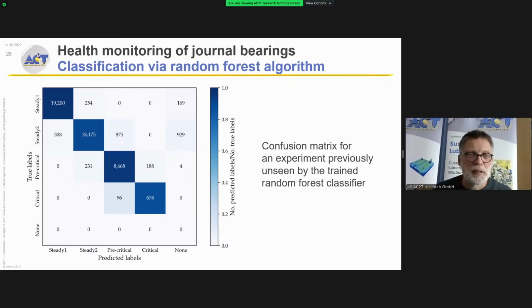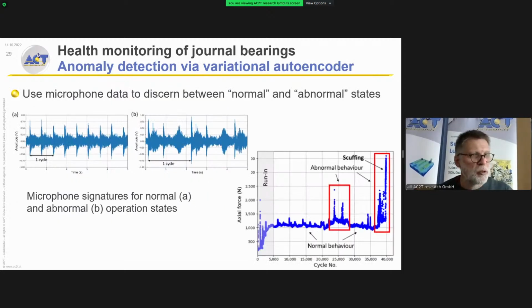Okay, so to go on, as a next step, we took the microphone data and tried a different approach using what is called a variational autoencoder, which is a neural network, to try to detect at least 2 states, called here normal and abnormal. The normal states would correspond to what was called steady 1 and steady 2 before, and the abnormal state was all the rest. We tried to use the microphone signatures to train an algorithm to predict when abnormal behavior is happening. This was done in cooperation with our scientific partners from Switzerland, from the EMPA in Thun, and they developed the algorithm together with us.